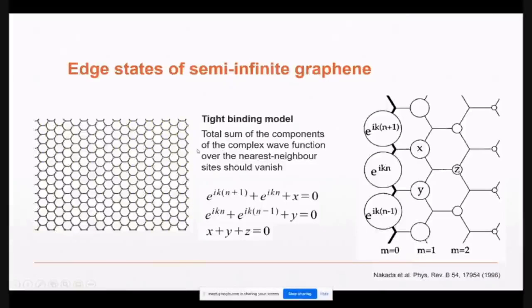Okay, good. So if you see my cursor, this is called a zigzag edge, and the bottom one is called an armchair edge, because of the topology of the carbon atoms. If you simply do a standard tight binding model calculation, it's very easy. We just have to take the densities from every atom and simply add them up with appropriate boundary conditions and the condition of orthogonality. Then you will see something really interesting: these two edges behave very differently.